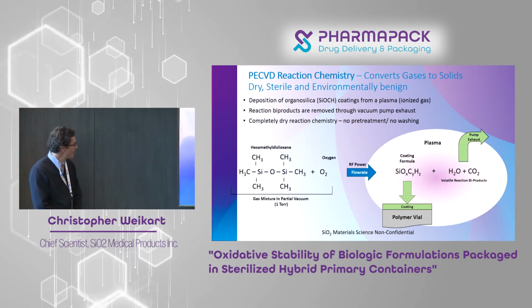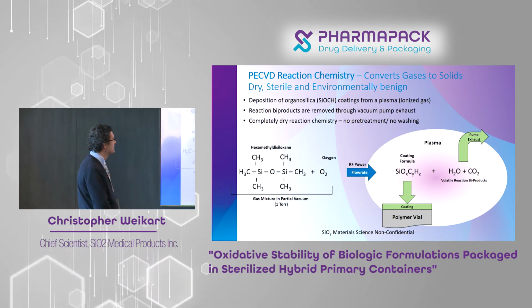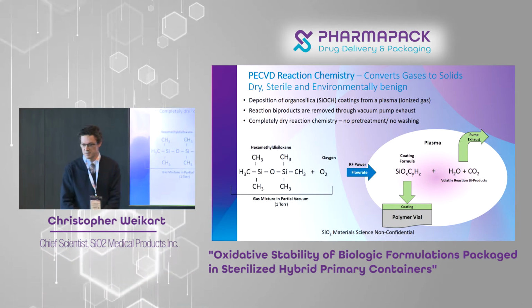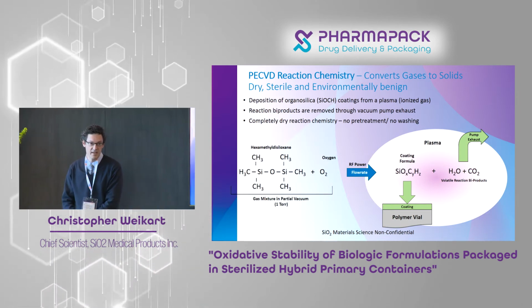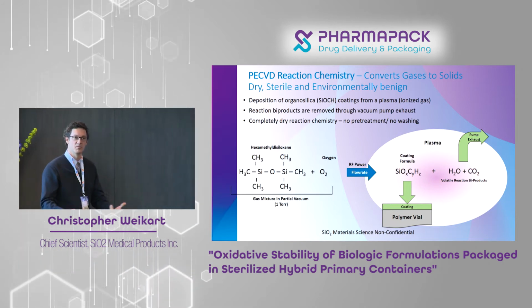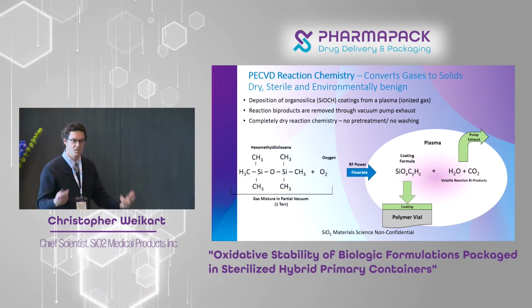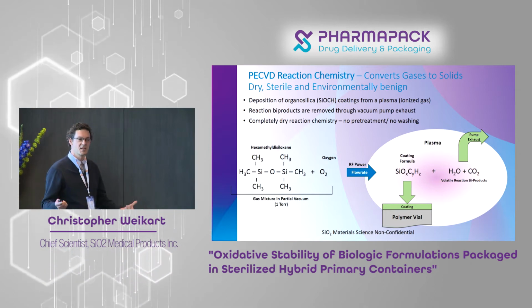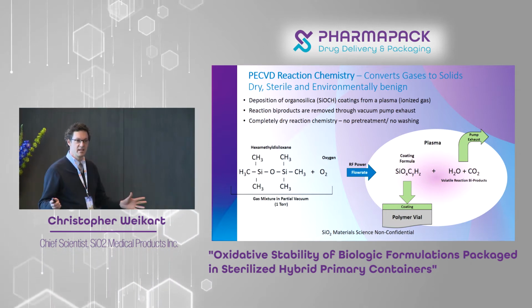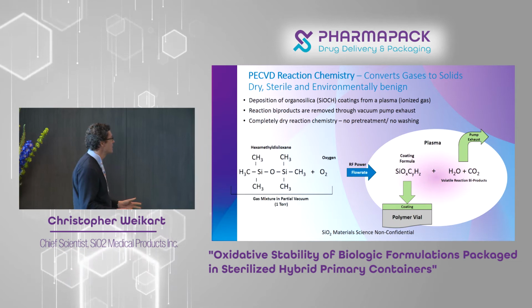So there's a little bit about the chemistry. I won't dig into this too much, but the key here, because I get a lot of questions about it: do you have to clean it, do you have to activate it, do you have to do anything to the part before you coat? And the answer to that question is no. It's a completely dry process, doesn't require any solvents, any cleaning whatsoever. We coat directly on the polymer.